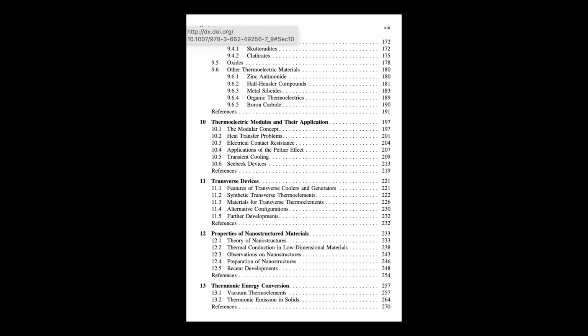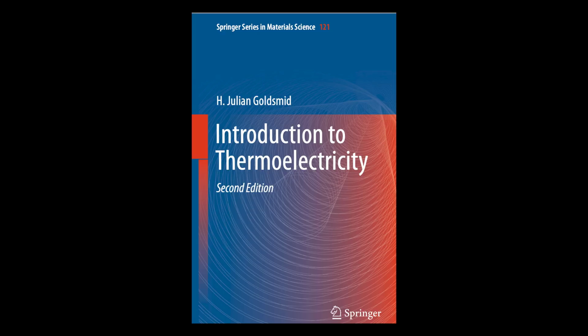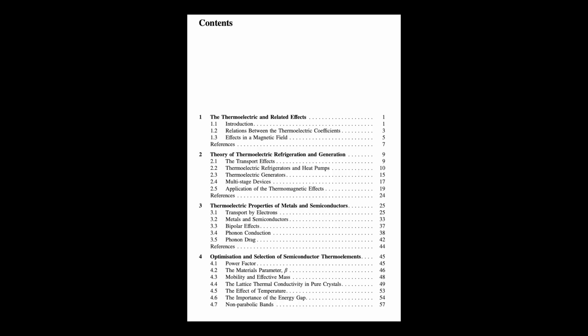Okay, so we've made the material. How do we measure its properties accurately? Electrical conductivity first. Right, fundamental measurement. To avoid errors from stray thermoelectric voltages, using alternating current, AC, is often better than DC. An AC bridge circuit lets you precisely measure resistance, and thus conductivity, by balancing impedances. The key is using a high enough frequency so any thermoelectric voltages don't really have time to build up during each AC cycle. Makes sense.